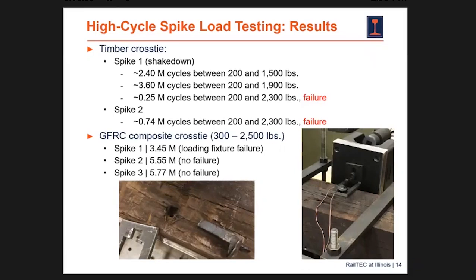Whenever we threw these spikes in the GFRC composite ties, we were then able to see that we were not able to reproduce the failures. We broke our fixture, and then we were able to load it for more than 5 million cycles on another couple trials, different spikes and different ties, and we're not able to reproduce failure.